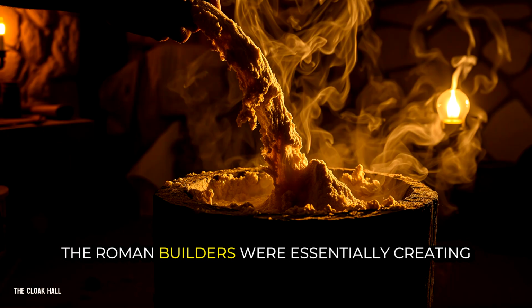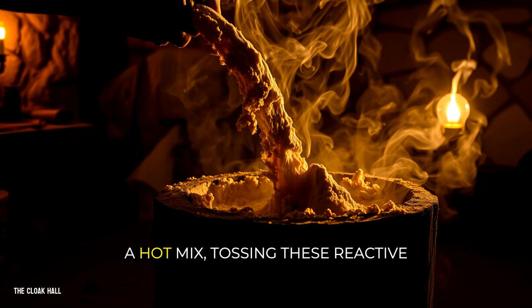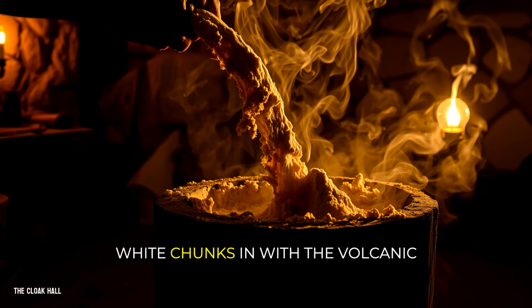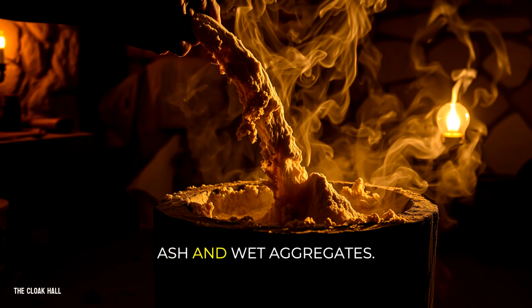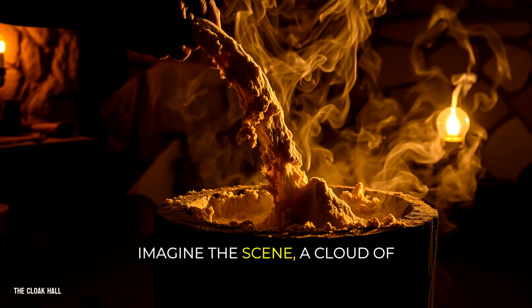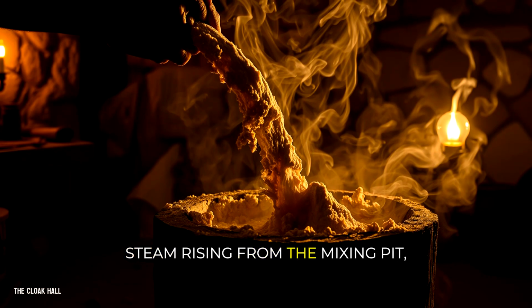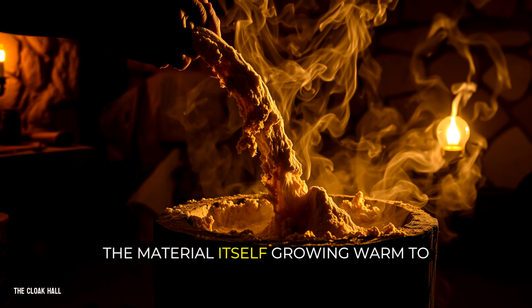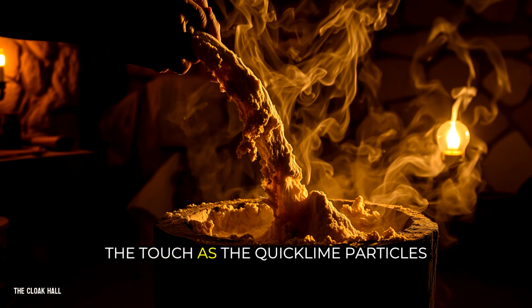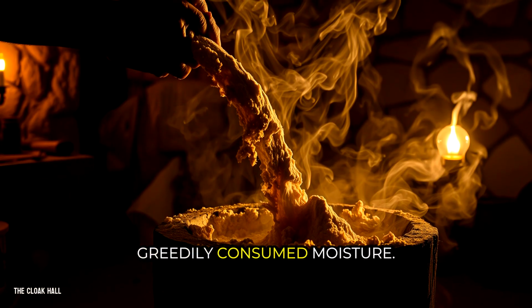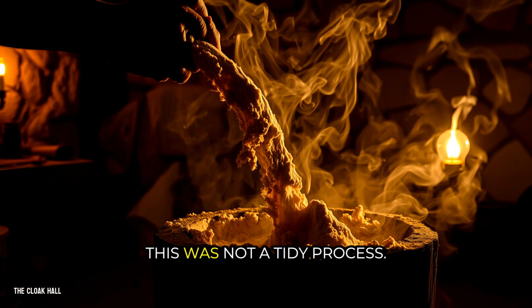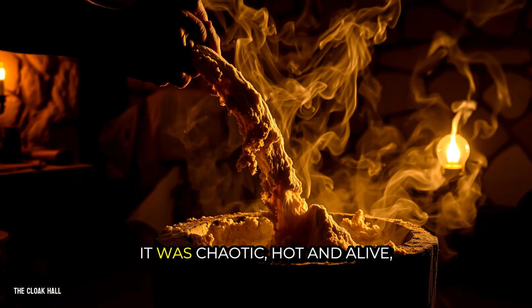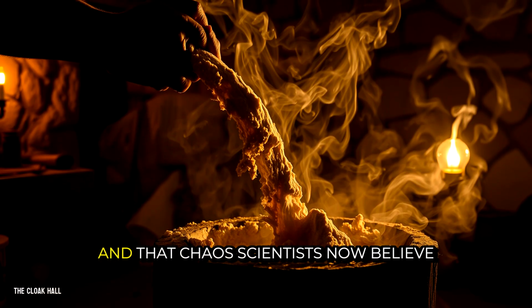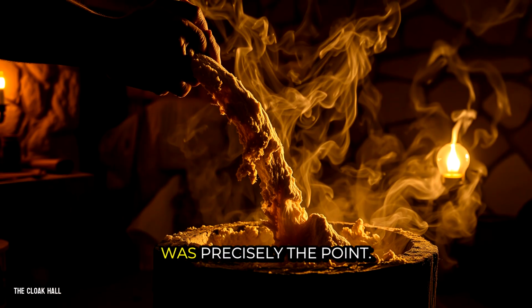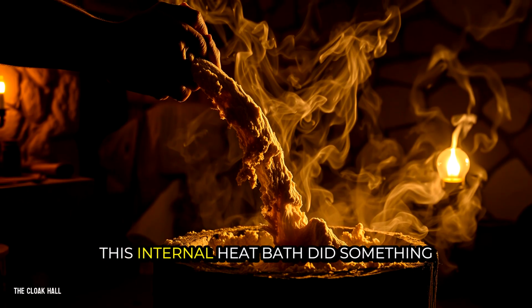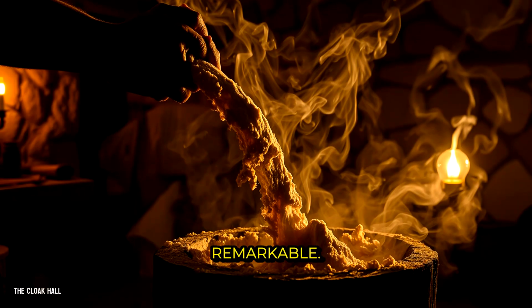The Roman builders were essentially creating a hot mix, tossing these reactive white chunks in with the volcanic ash and wet aggregates. Imagine the scene, a cloud of steam rising from the mixing pit, the material itself growing warm to the touch as the quicklime particles greedily consumed moisture. This was not a tidy process, it was chaotic, hot, and alive, and that chaos, scientists now believe, was precisely the point. This internal heat bath did something remarkable.